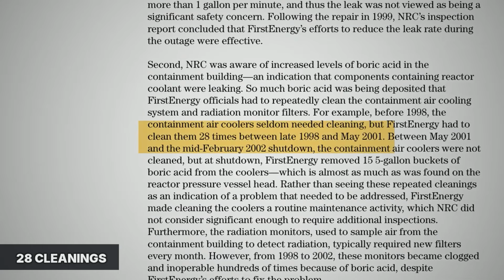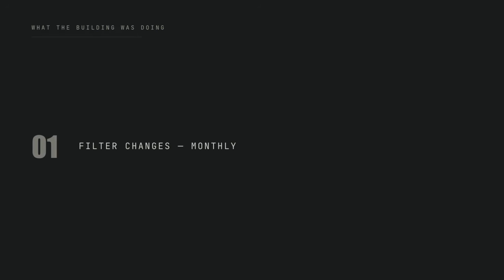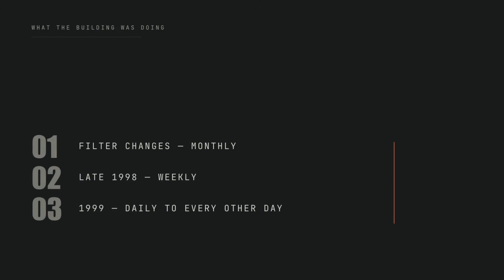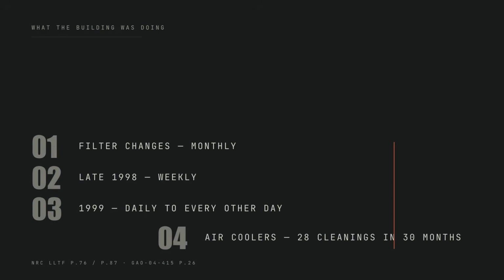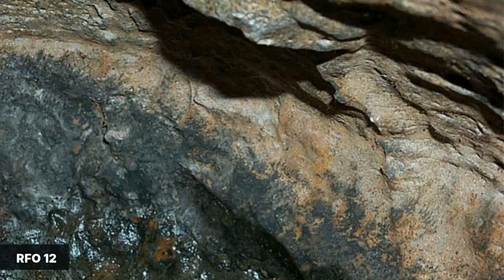Between late 1998 and May of 2001, First Energy had to clean them 28 times. The fouling was boric acid. Read those two facts together and you have a machine describing its own injury. Boric acid was not sitting quietly on a lid. It was airborne inside containment in enough quantity to blind a radiation monitor every 48 hours and to plug the air conditioning of the building 28 times in 30 months.